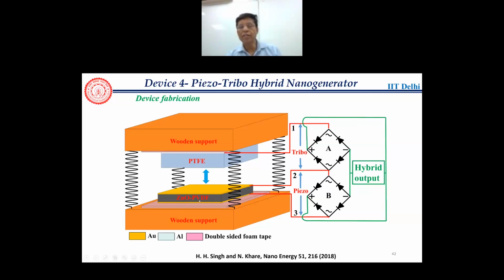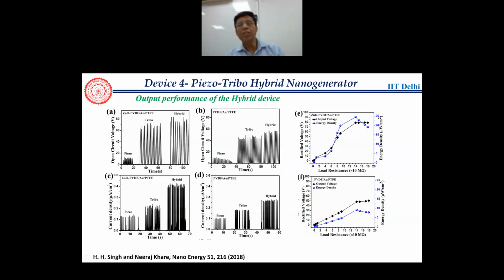And as I explained, the advantage here is that since the beta phase gets large, we can have more piezo or ferro effect in these nanocomposite films. So what happens basically? You see in the structure of the PVDF, we have these CH2 and CF2 dipoles, and sodium niobate nanorods, when mixed with this, basically interact with CF2 dipoles and try to align them because of their own ferro property. And similarly, this RGO interacts with the CH2, and that also helps in the alignment. So that is how the beta phase of this material gets enhanced once we have this sodium niobate and RGO present in this material. Similarly, zinc oxide also interacts with the CF2 dipoles and tries to align them.